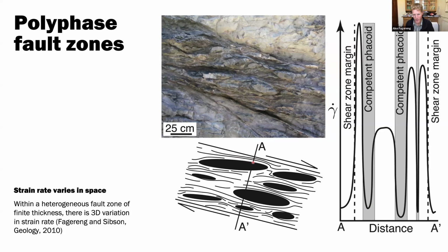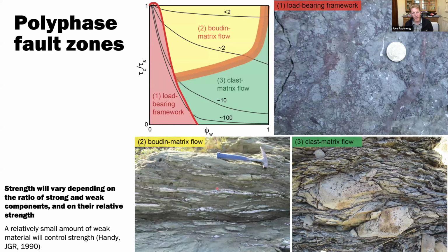And inevitably, there is then going to be a strain rate gradient at the edge, and you have effects on the bulk strength. So obviously, this is a bit stronger than having just the flowing matrix because of the clasts increasing the strain rate that has to be taken up by the weak material. But equally, it is weaker than if you had just the strong material, because a lot of shear can be distributed through the weaker component.